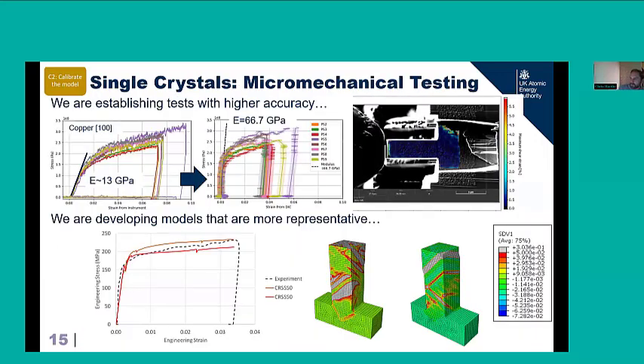Moving forward, we're then looking at developing or improving techniques to best calibrate these crystal plasticity models. And one way to do this is to make the mechanical test so small that you can test individual grains in a polycrystalline sample. So on the right is a video showing a micropillar compression test in pure copper. And my colleague Luke has developed a means of doing the same high-res digital image correlation on the surface of